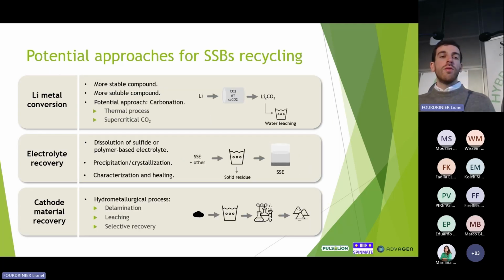So for the lithium metal, what we are going to study in these projects is the conversion of the lithium metal into another compound which is more stable and also soluble in water, which is the lithium carbonate. So we will have this process that is called carbonation. And by doing this, at the end, we will have a material which is, as I said, more stable than the lithium metal, and that is soluble in water. And it means that we can use water as leaching agent to recover it and further precipitate. There are different possibilities to do this. We will try thermal process with a CO2 atmosphere. We will also try supercritical CO2. And you can also try to do this shredding under a CO2 atmosphere.